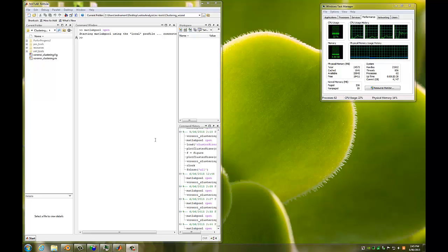The way that a concentration field is defined in this case is by the volume that each atom we're testing the clusters for is uniquely occupying in space, which is its Voronoi cell. This distribution is, of course, much more useful than, or has a lot more uses than just cluster analysis. But cluster analysis is one of the most straightforward ones.